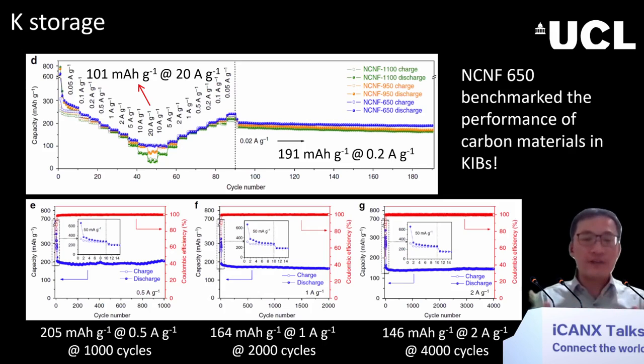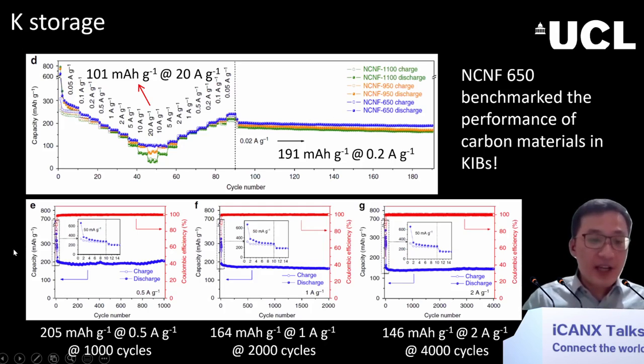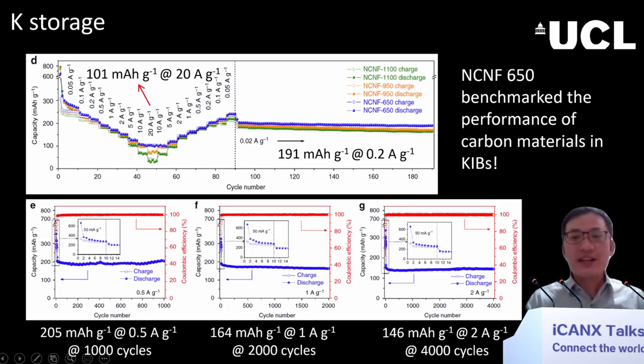We also tested the 650 degrees material at various current density and various cycles. The performance is quite impressive. At low current density, the capacity was very stable over 1,000 cycles, and at a high current density, the capacity is also stable over 4,000 cycles. By the time the paper was published, which is already 2 years ago, this performance actually benchmarked the performance of all carbon materials in the area of potassium ion batteries.